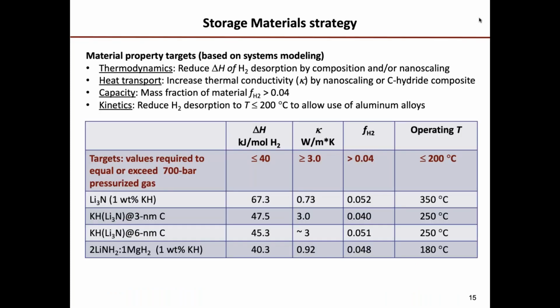So our strategy from a materials point of view is to do basically four things. We need to reduce the thermodynamics, that is the heat required to desorb hydrogen, to a value that is low enough that will allow us to operate at these lower temperatures. We need to improve the heat transport, that is the thermal conductivity, so that we can get heat in and out of this bed and drive off the hydrogen or regenerate the material. We need a capacity above a mass fraction of 4%. And we need to have kinetics that are fast enough that, again, we could drive the hydrogen release at less than 200 degrees C.